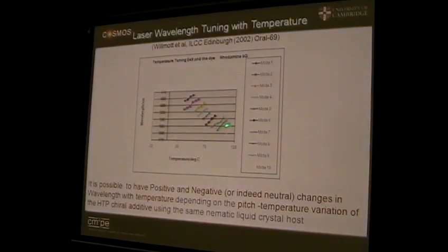And they're kind of neat, because they're actually interesting physics. As you're cooling the system, the helix is flipping a half turn as it accommodates at the lower temperature and the helix pitch changes. So what you're seeing there in those different, what John called different modes, are actually half turns of the chiral nematic helix jumping down, etc.